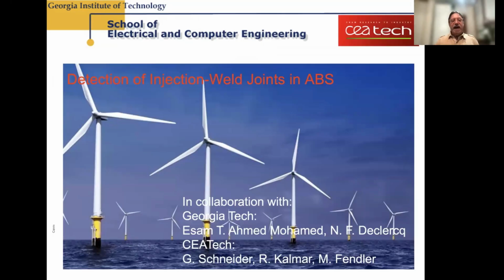Lastly, before we move to packaging, we can do some other interesting things. For instance, detect injection weld joints in plastics or thermosets. And the reason this is interesting is because when plastic is injected into the mold and the different flows meet, where the flows meet is the weld joint. And sometimes it's very difficult visually to detect the weld joint. And that's usually the point, or a region where